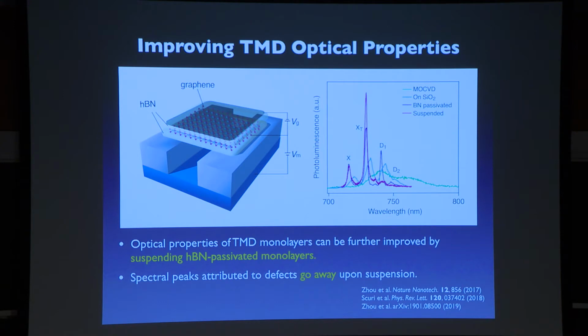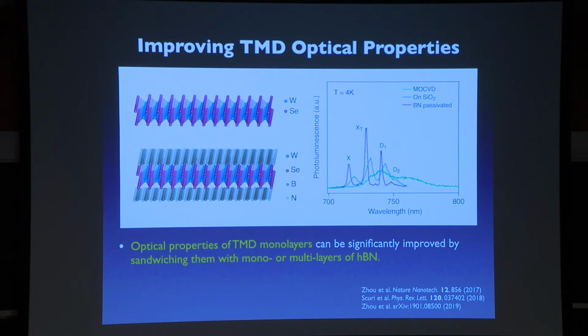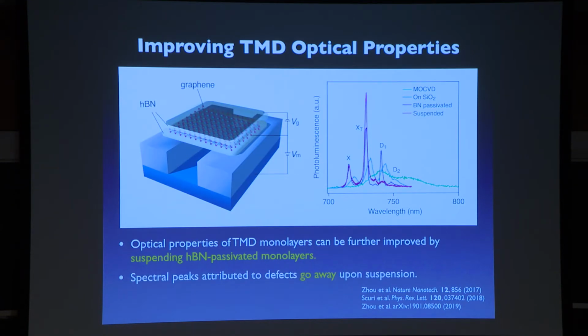Why do I say that these properties are even better than what we got previously in this particular spectrum? Well, width-wise, it's not that much better. But once you start to suspend them and eliminate the substrate, some of the spectral features just go away. What does it tell you? Whatever this was, it is not coming intrinsically from the material itself, because the only thing that we changed was to remove the substrate. Some spectral features stay the same, while some of the other features go away. So this must be coming from some interactions with the substrate.